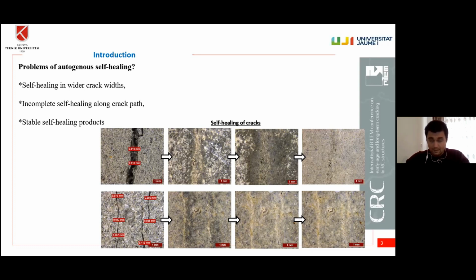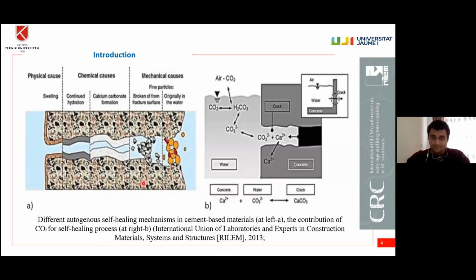Here is another study that we made. This matrix is composed of carbon nanotubes and nanosilica, and you can see that up to 1 millimeter crack you can get autogenous self-healing. But you know, these comprise some complex matrix compositions, and therefore this can sometimes be a concern in terms of cost efficiency. So instead of that, what can we do? What we can do is to synergistically use mineral admixtures for effective autogenous self-healing.